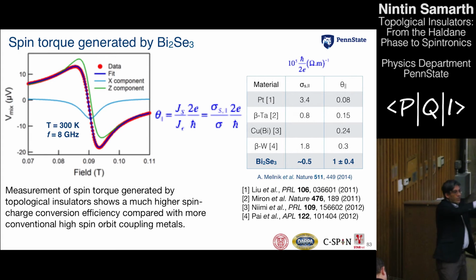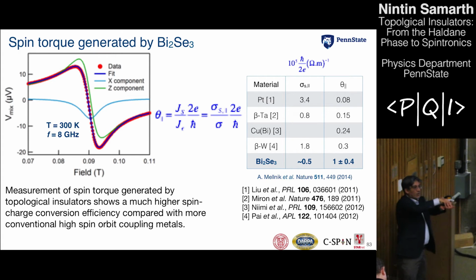you have two conductors which are in parallel to each other. It turns out that the resistivity of the metallic ferromagnet is much higher than, conversely, the resistivity of the bismuth selenide is much higher than the resistivity of the metallic ferromagnet. And so most of the current flows through this metallic ferromagnet. And that makes the analysis of this data somewhat complicated, and that's what generates this large error bar in this case. But the data are quite impressive because this occurs at room temperature, and you get a parameter value which is very, very intriguing and promising.